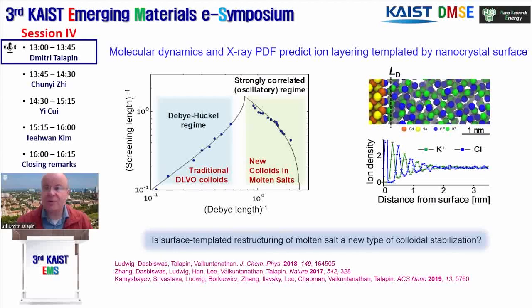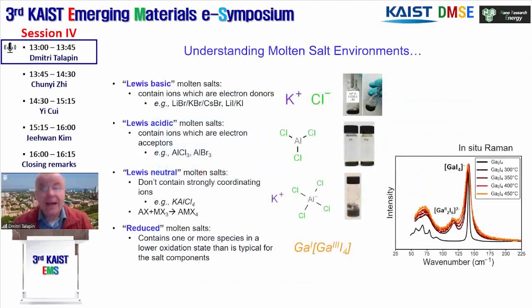in molten salts, we switched to a completely different regime of electrostatic interactions in solutions. So typically, when we have dilute electrolytes or solutions with relatively large Debye screening lengths, the electric field decays exponentially into solution, and that is described by the Debye-Hückel regime. And that's where all traditional colloids operate. But if we go into very high concentration electrolytes, the electric field is not decaying exponentially into solution, but it starts oscillating and propagating further beyond the Debye screening lengths. It is a regime that is not accounted for by Debye-Hückel. It's not accounted for by DLVO theory. It's a new regime where the interactions extend about an order of magnitude beyond the Debye lengths, and these interactions are responsible for colloidal stability.